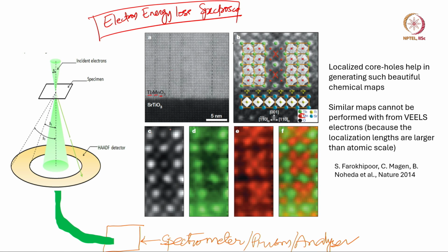The green ones, these big atoms, are terbium atoms, and in between these 4 terbium squares there will be manganese. I think if you look carefully you can see it, right. There is a small manganese dot in between. So, there are 4 terbium atoms like this and in between there is a small manganese dot. Okay. And then there is some sort of a defect here, right, and in this defect